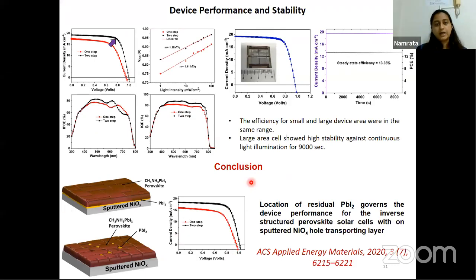So when we further characterized the device for the JV parameters, we can see that the JV curve for the two-step is clearly much sharper, and we have a closer value of the ideality factor for the two-step deposited perovskite. And looking at the IPCE and the IQE spectra, we can see that we have a higher IPCE coverage, and IQE also increases.